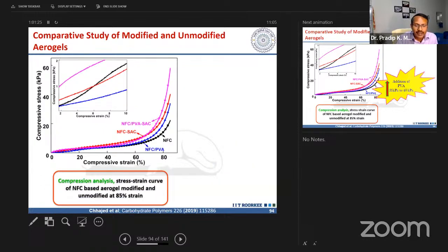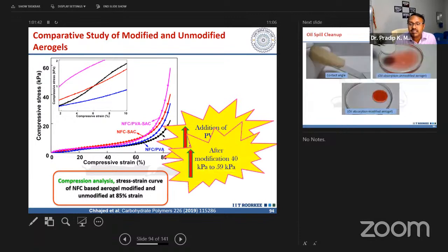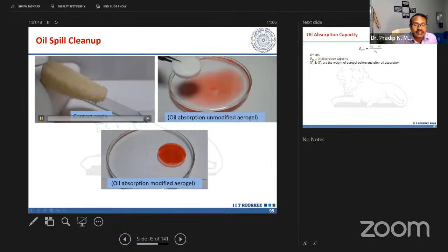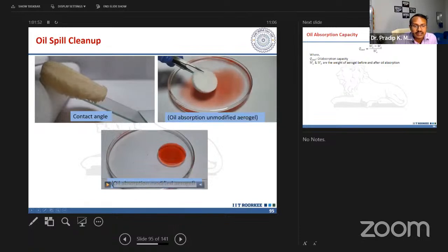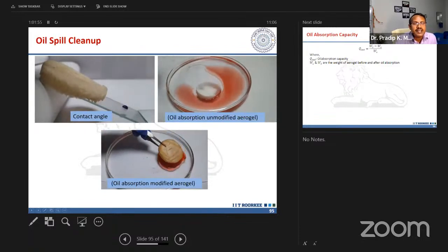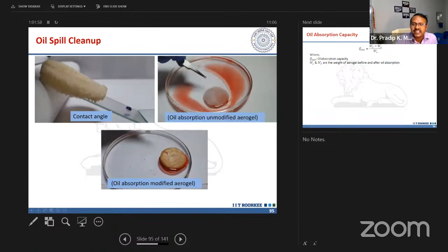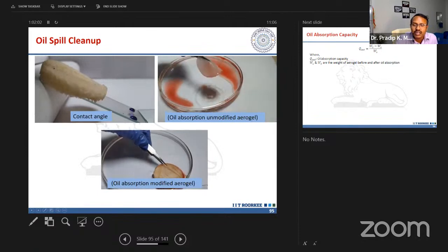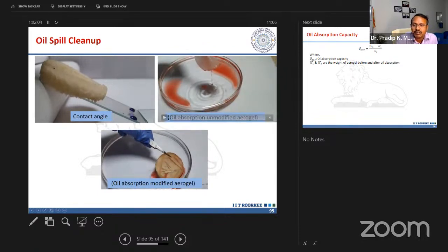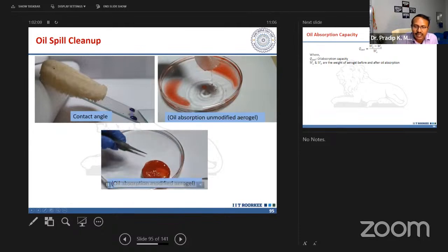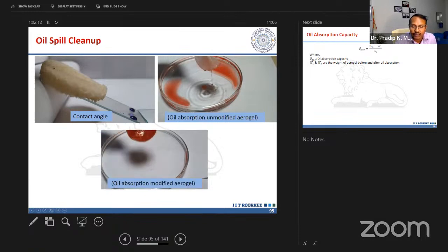From the mechanical point of view, it is supposed to be strong enough. The NFC PVA modified material has very good mechanical properties compared to the unmodified material, which is also strong. After the modification, we are getting 40 kPa to 59 kPa. Now just see the video of the contact angle and oil-water separation. Whenever we put it in, the unmodified material takes water and oil, while the modified material takes only oil. We have used some castor oil with some pigment or colorant so that we can distinguish it. You see, it is taking the oil. We have stopped it here.